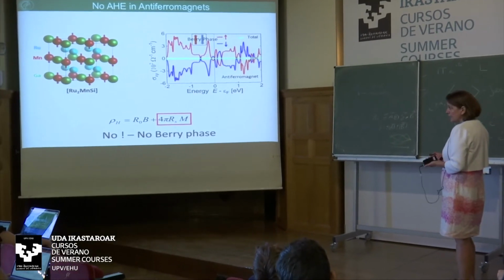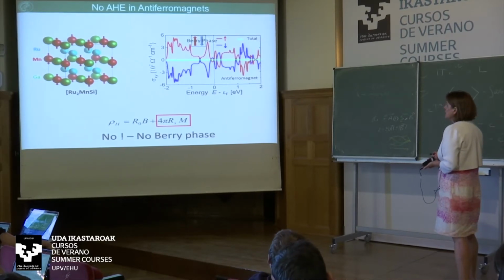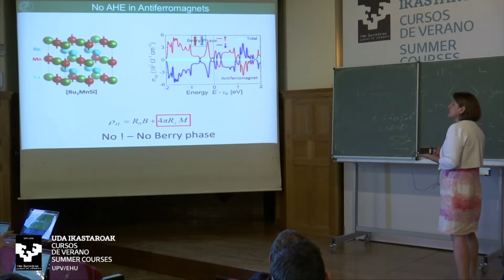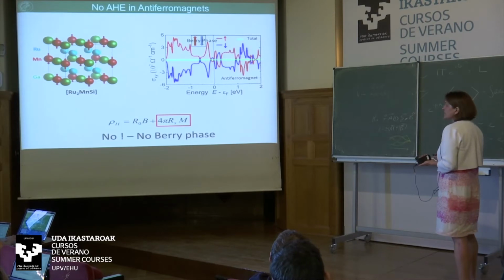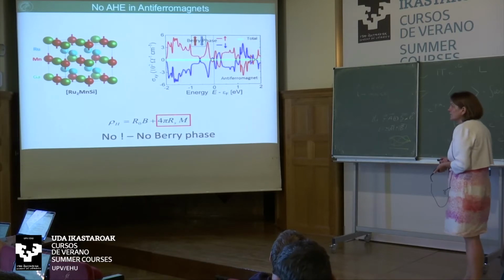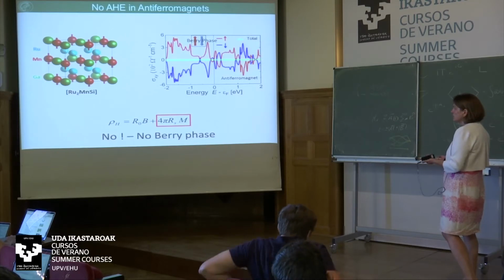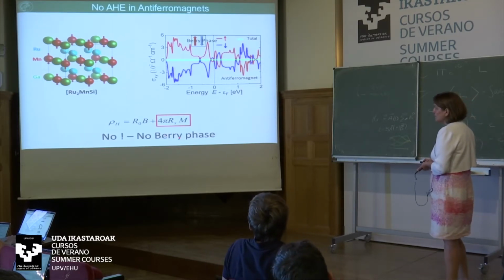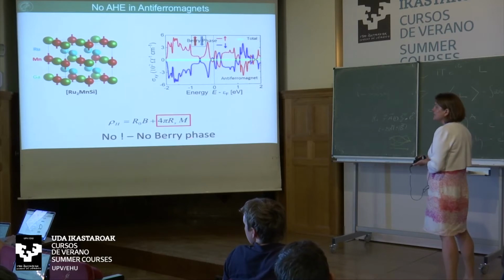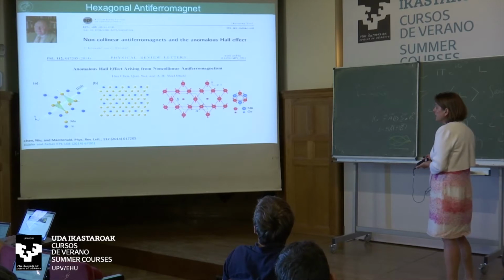So in an antiferromagnet, we have really no anomalous Hall effect. Here we take simply an antiferromagnetic Heusler, and you see the Berry phases for both spin directions. Over the whole energy range around the Fermi level, everywhere it cancels out to 0. This is symmetry related. So we always believed, okay, antiferromagnet, no magnetic moment, this value has to be 0. So can we make antiferromagnets where this is not 0? Indeed, we can do this, and one example was manganese 3 tin.